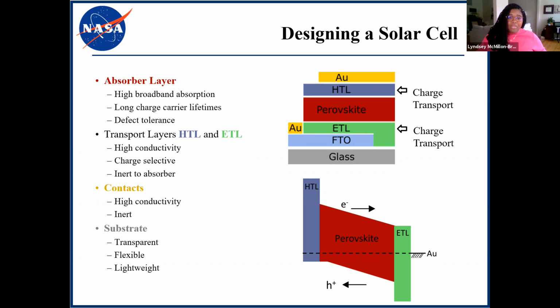I have on this diagram here FTO, which is fluorine doped tin oxide. That's a chemically inert charge selective contact. And ideally it would have high transmission, good conductivity. And really we use it because it promotes adhesion for the subsequently deposited layers.